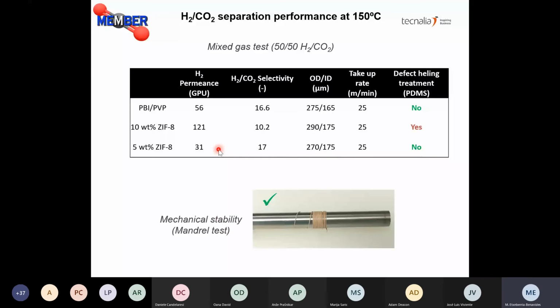And so in order to decrease the number of defects of the selective layer, we decided to decrease the ZIF-8 concentration to 5%. We obtained a selectivity of 17, but the permeance is below the permeance of the pure polymer fiber. So we think if we further optimize the spinning process, we will be able to increase the hydrogen permeance, keeping the selectivity constant. Regarding the mechanical stability, this fiber successfully passed the mandrel test. As you can see in this picture, we were able to wind the fiber in the tube without breaking it.